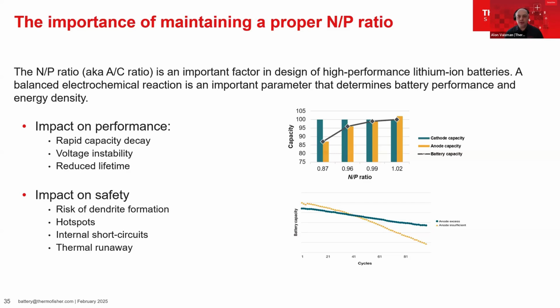An incorrect N to P ratio can speed up capacity decay and reduce the lifetime of the cell. It can promote formation of dendrites, hotspots, and in extreme cases lead to thermal runaway. Close monitoring and tight control over the active material loading uniformity is of increasing importance, but until recently, the tools available to process engineers and quality teams for measuring the electrode loading were limited to single point or scanning sensors.